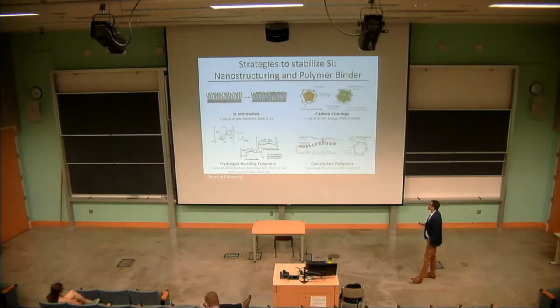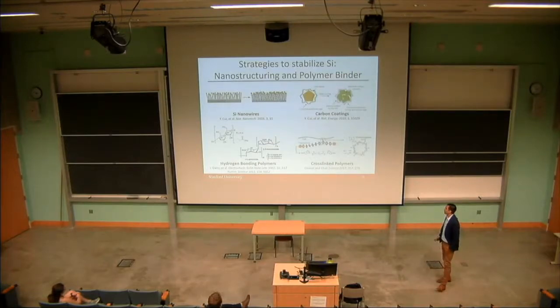Another approach that's quite popular and shown quite high performance is to have some sort of carbon coating around your silicon active material, and what that does is that protects the silicon as it fractures, and so you end up with a secondary particle of fractured silicon inside a carbon cage. And that allows all of these fractured silicon parts to maintain their electrical connection and protects the new surface from solid electrolyte interface formation, because that happens actually at the carbon interface that doesn't change over time.